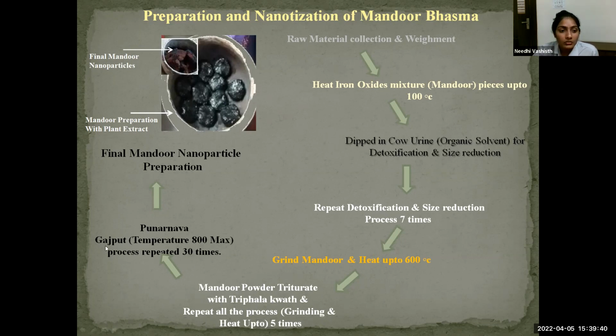Then Punarnava Gajput heat temperature is maximum 800. The process is repeated 30 times. Gajput is like a furnace whose temperature is taken up to a maximum of 800. Finally, Mandoor nanoparticles are prepared. We see in the image the final nanoparticles. Mandoor nanoparticles are like this, and this is the Mandoor preparation with plant extract.